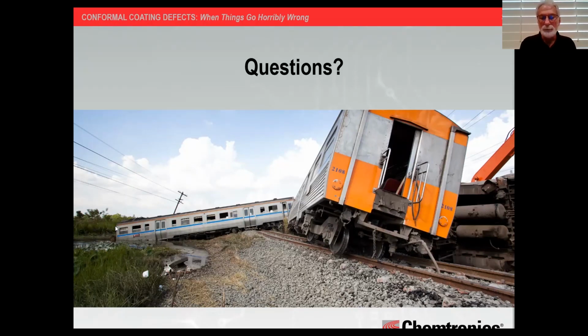What you have to realize is that as the coating liquid, as those solvents evaporate and that coating becomes more solid, that surface tension is constantly changing from the time you apply it until the time that it is totally cured. When I say the surface tension, what I'm talking about is like the initial coverage of the substrate with the coating. Because once that's on there and it's flowed, it's wetted, it's starting to bond, then that property of surface tension, when you first apply it, has done its job.